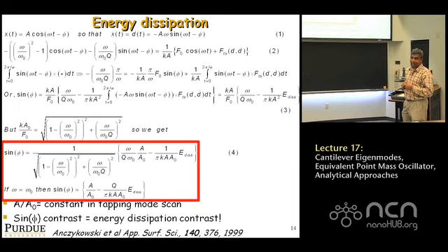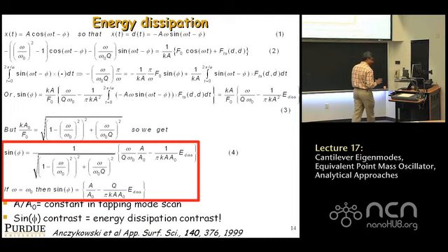Sine of phase is basically giving you energy dissipation over the sample. Fantastic. Energy dissipation between a few hundred atoms as they quickly approach and move away. Amazing, if you think about it. I still get excited by the very thought that you can measure this. And these numbers are typically, in air, a few electron volts. It's just amazing, it's really remarkable. Or picojoules, if you like, mechanically thinking about it.